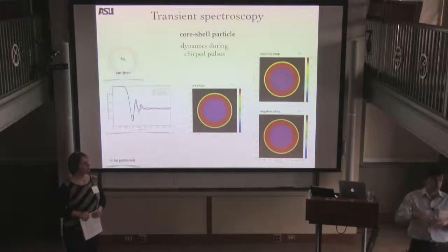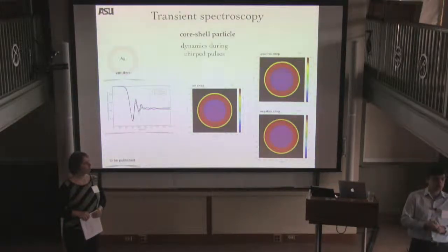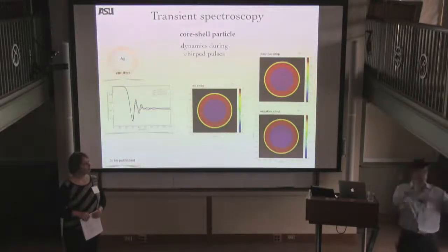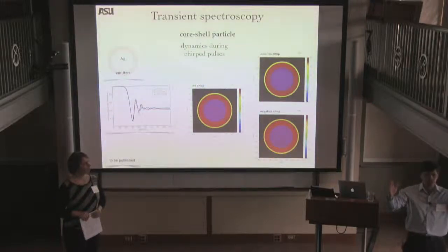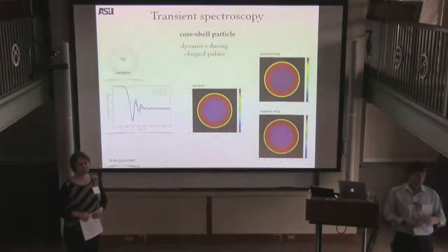So our intensities are high enough to see the Rabi cycling, but not high enough to change the dielectric of the metal. Now, what we use in our case for epsilon is a Drude-Lorentz model with approximately 18 fitting parameters, such that we cover the entire range of frequencies from 0.5 all the way to 5 electron volts. And it's not only Johnson Christy. I forgot that another paper recently appeared. It's tabulated as well for the epsilon, so it's more precise than just Johnson Christy. And those many parameters are obtained by fitting to the real part and imaginary part, yes, that's right. Absorption. Yes, that's right, n and k.